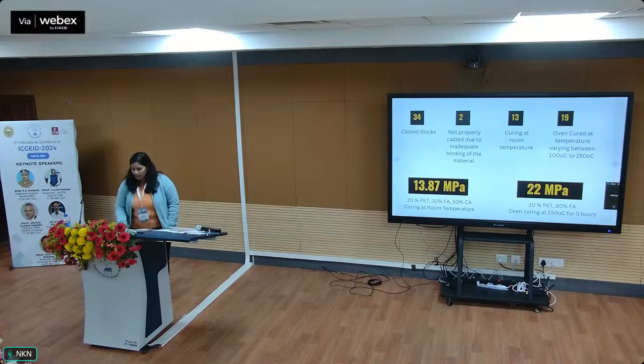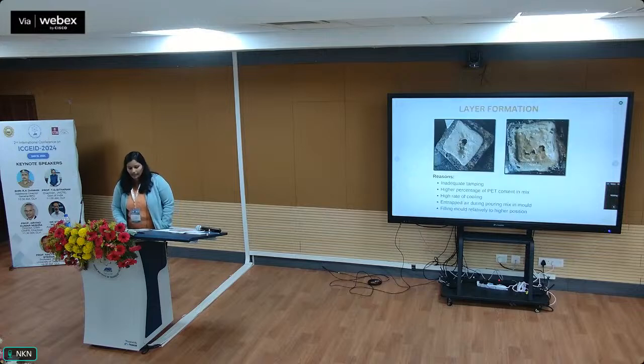While casting, there are certain problems which were encountered, like layer formation. While casting we observe that there is a formation of layers. There are certain reasons behind this layer formation. There might be inadequate tamping, or a higher percentage of PET content in the mix. Because of the higher percentage, there is a higher rate of cooling at the surface, so the layer at the outer surface is cooled before the inner material. Another reason is entrapped air and filling the mold relatively to a higher position.